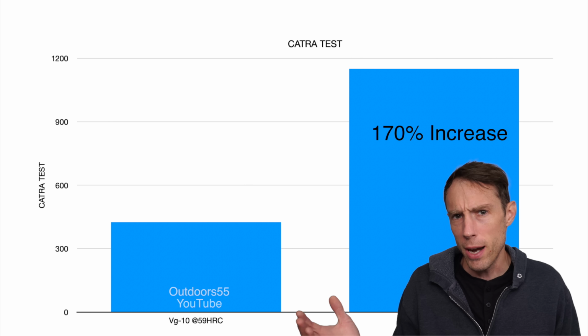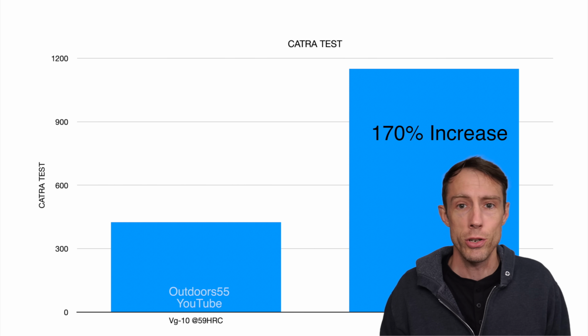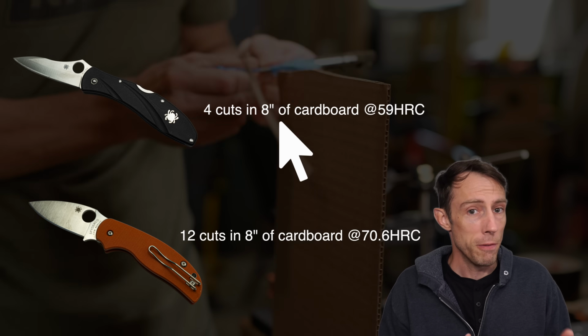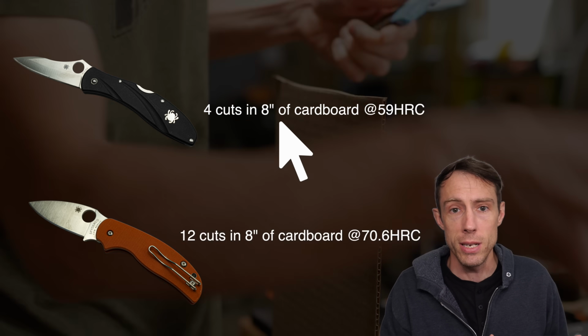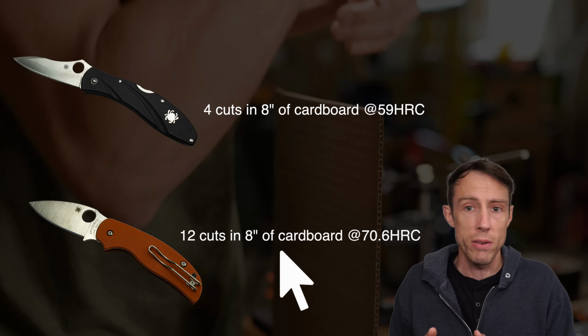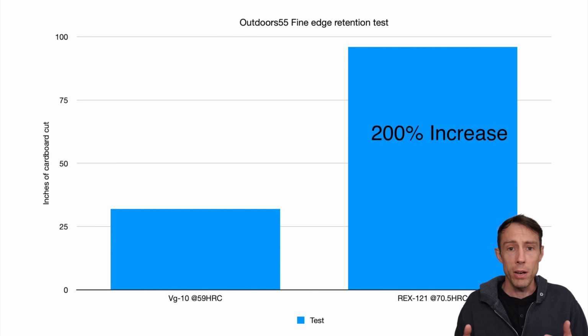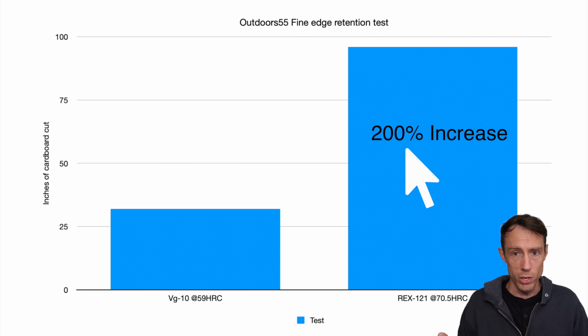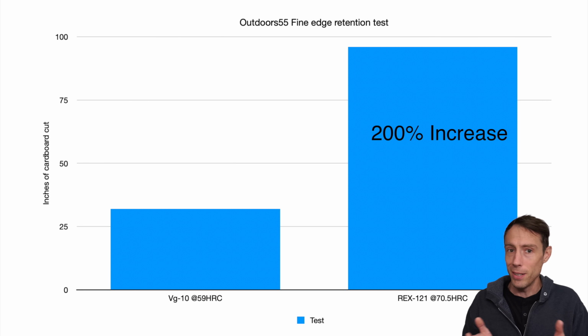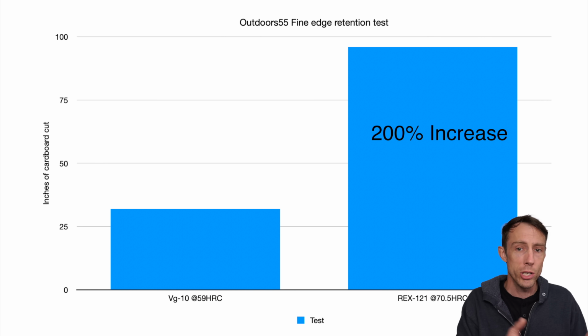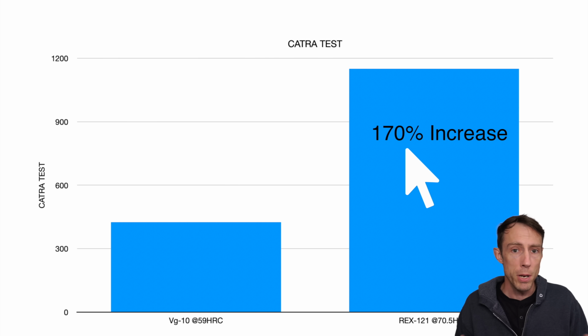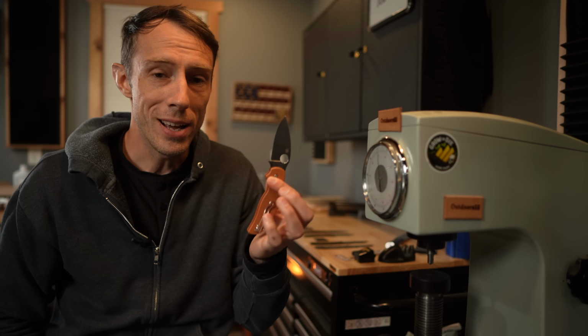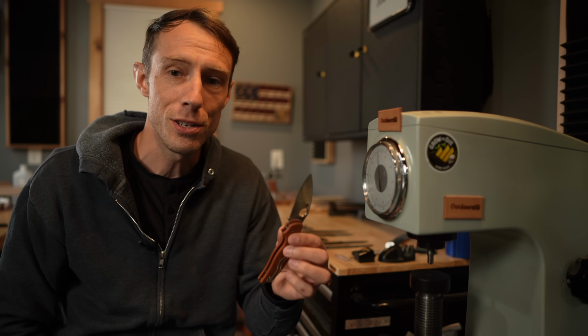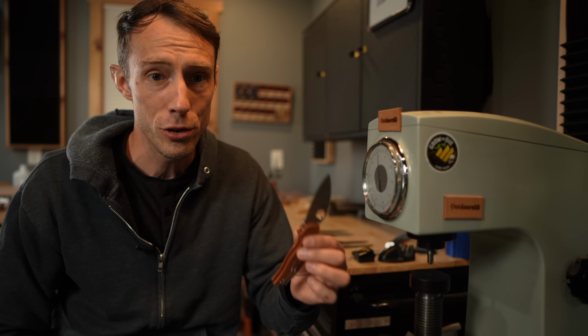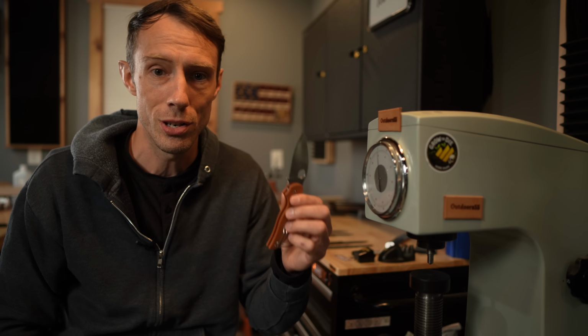So how does this compare to our fine edge retention test that we just did? Well, in my test, 4 cuts for VG10 at 59 HRC to 12 cuts for Rex 121 at 70.6 HRC gave us about a 200% increase in edge retention. Now this is actually surprisingly close to what the Knife Steel Nerds chart says that it should be, especially considering my fine edge retention test isn't the most precise test. So edge retention wise, I think that everything that you've heard about this steel is true. This thing is an absolute edge retention beast.